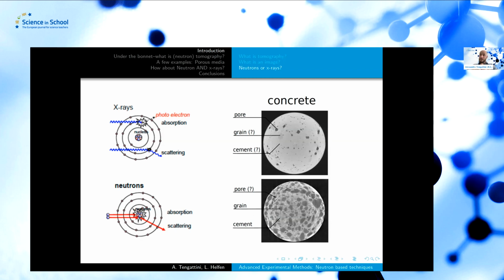But when we do the same thing with neutrons, all of a sudden, the grains, because they are made of quartz and oxygen, are very transparent. So paradoxically, it's very easy to distinguish the cement from the grains, but all of a sudden it's the pores and the grains that are too similar to be able to easily distinguish. So you can start seeing that these two techniques are incredibly complementary.